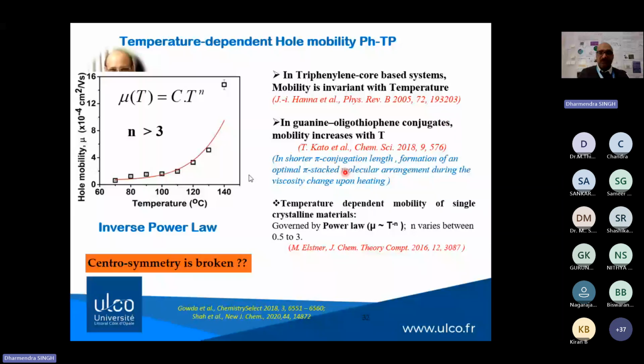Our system was completely surprising. We repeated this experiment several times, and after that we went into the literature. The mobility behavior of a single crystalline material is governed by the power law. But our system is not a single crystalline, crystal-like system. This is a disordered system. When we fitted the data, it followed the inverse power law. The inverse power law was associated with centrosymmetry breaking. Later on, I will explain what centrosymmetry is. Basically, this temperature-dependent mobility was associated with the centrosymmetry breaking of the compound.